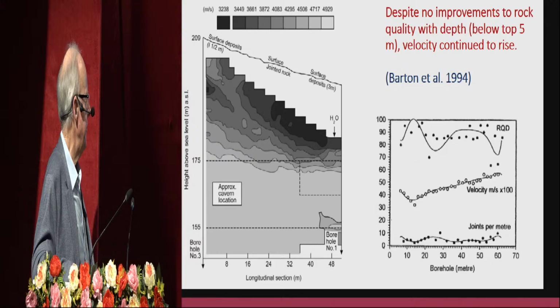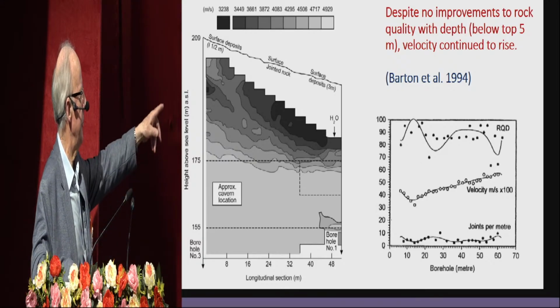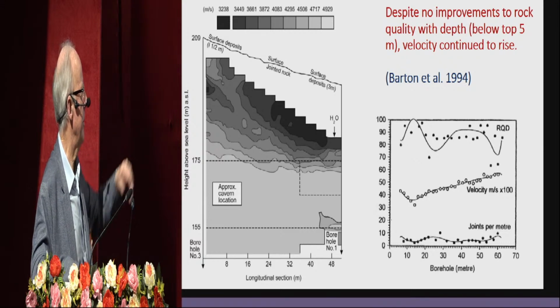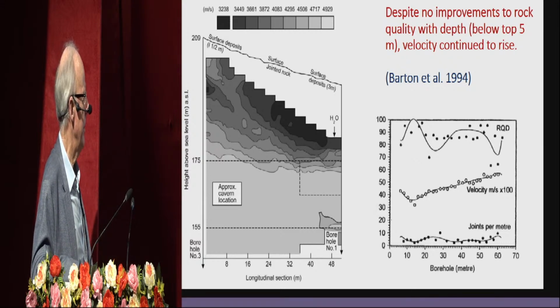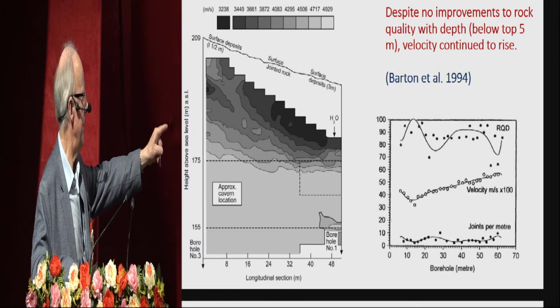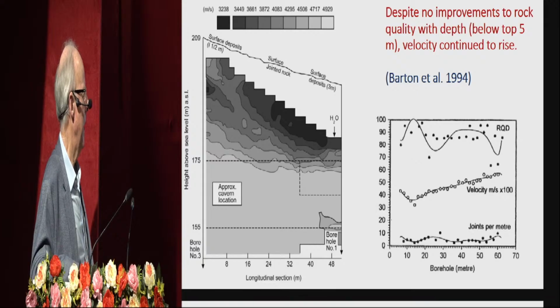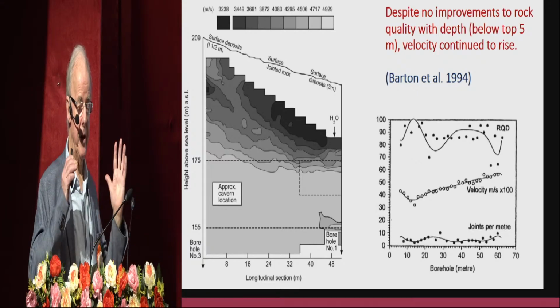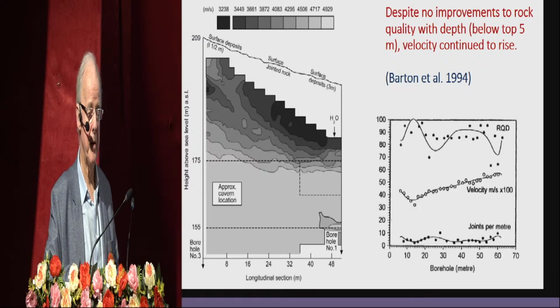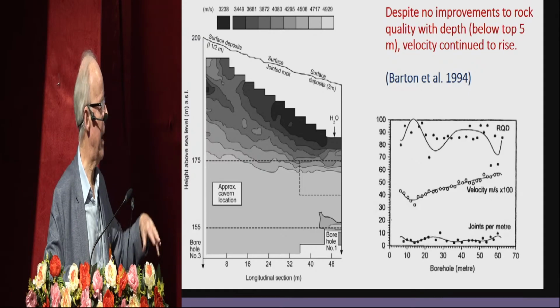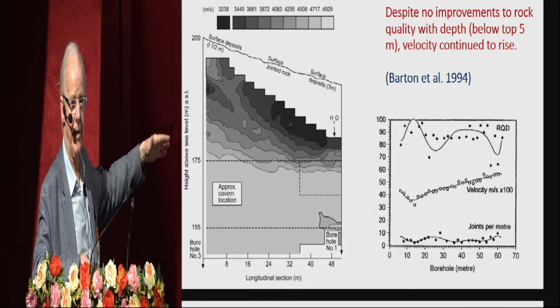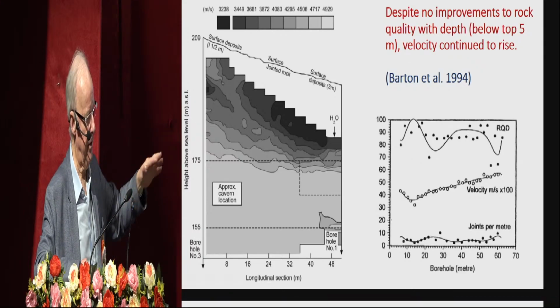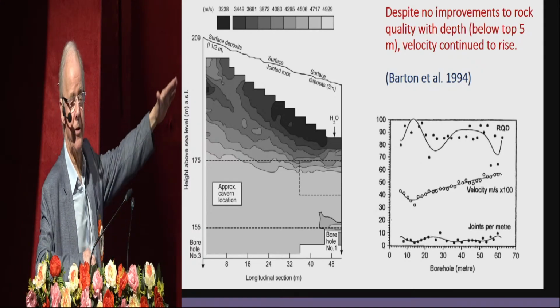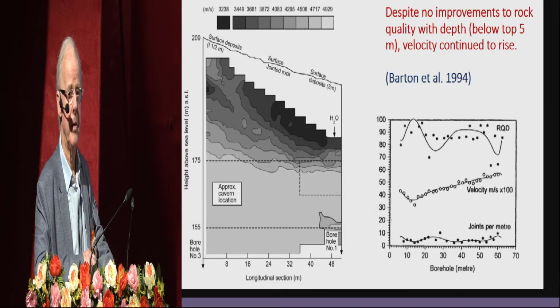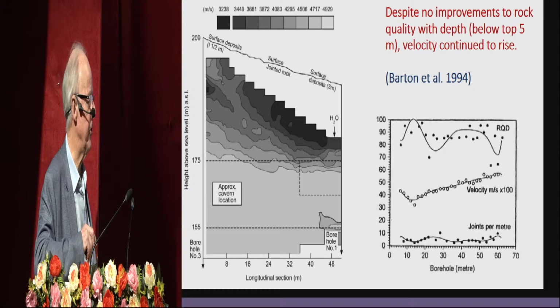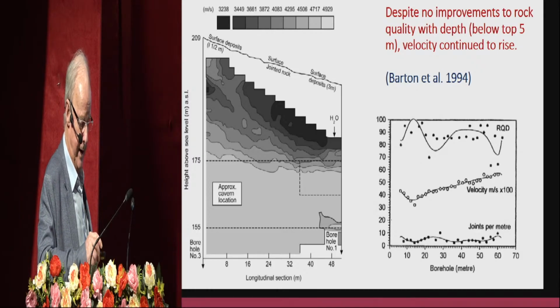So the strange thing is that when you go down one of these boreholes, the RQD is just varying up and down around 80 to 90 to 100. And the joints per meter on the bottom is just varying between a few joints per meter. There's not a trend for increasing spacing with depth, right? And the RQD is not improving with depth. And the Q value is also not improving with depth. It looks similar to the joints per meter result, except it's between 5 and 25, going like this, not increasing with depth. But the velocity is increasing 2 kilometers a second with depth, just because of the stress closing the joints. So modulus has to be corrected also because of depth.